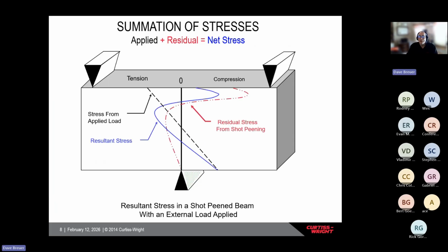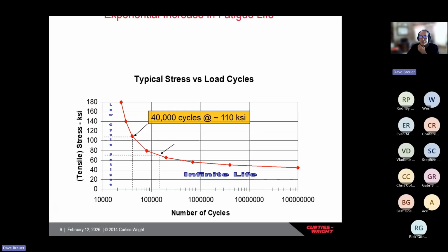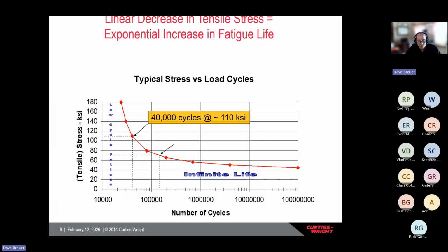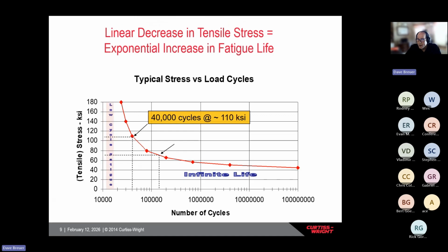Typically, when you shot peen anything, you improve the fatigue life from 3 to 5 to 10-fold. Some people will say that seems really strange, that you hit this metal surface with these little BBs and it lasts 5 times longer.